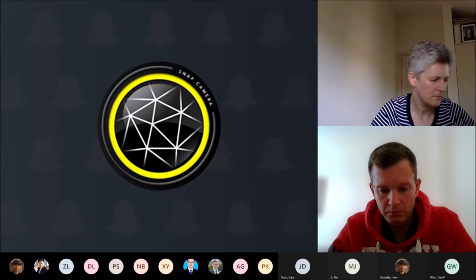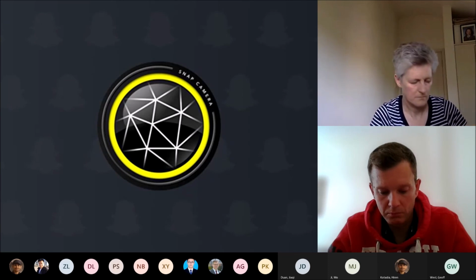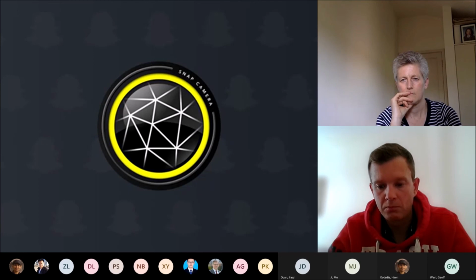However, based on our findings, the morphology from the surface we look at is all equiaxed. And if I say that the cross section or these elongated grains have an effect, we cannot prove that, because that elongated grain appeared as hot rolled. When you cold roll the material, it will be completely the sheet on the cross section. It will transform to alpha fiber and gamma fiber. That's why you saw on the cold rolling very large deformation bands. These elongated grains, after the cold rolling, will disappear, because most of the unit cells will be crushed until the 110 is parallel to the normal direction.